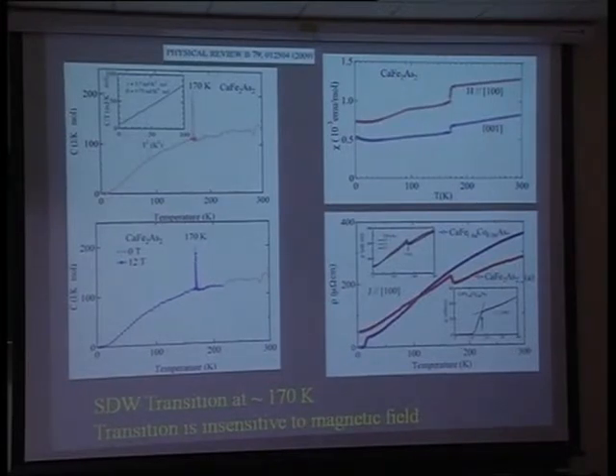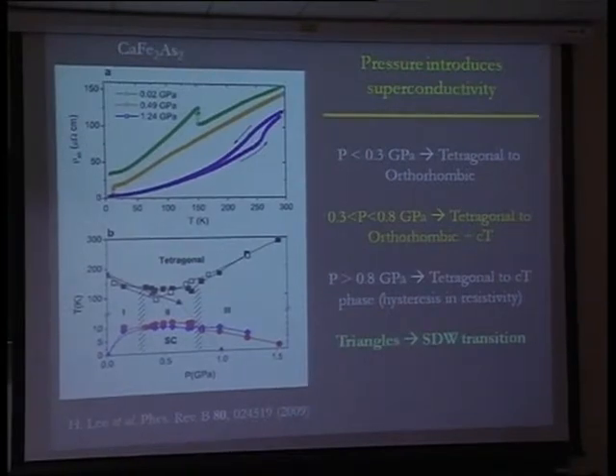Now you can of course dope this system by cobalt, nickel and so on and make superconductivity. But this calcium iron two arsenic two parent compound itself shows many interesting behaviors. For example, if you apply a very small amount of pressure, it shows superconductivity. This is very interesting in the sense that even if you put europium here, which has a very strong local moment, and you apply a small amount of pressure, it shows superconductivity. Here, it has been shown by this paper that if you apply very small pressure, the TC goes up, and of course there is an interesting structural phase transition, and the TC is almost maximum around say 15 Kelvin or so, and then again goes down if you apply much higher pressure.